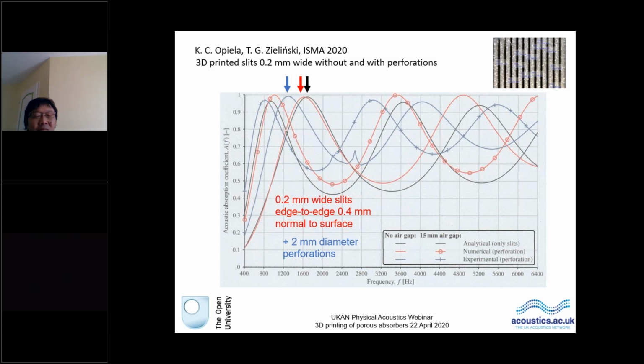What is interesting is that the perforations, these quite sizable perforations in diameter compared with the width of the slits, move the low frequency absorption peak to a lower frequency, which is always something that you're looking for in a thin layer. And they've been able to model it by using the representative volume elements to deduce the Johnson-Champoux-Allard parameters needed to predict the absorption.